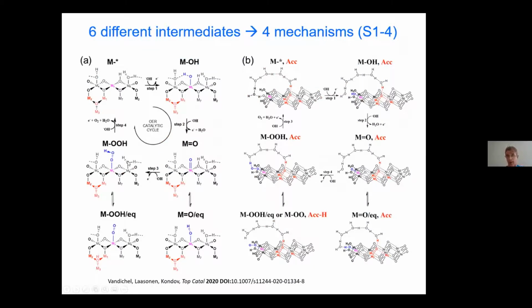So again, different states have been investigated. It's always quite similar methodology. Now, the hydrogenated acceptor site has been named as an equilibrated metal OOH species. And we can also work with an equilibrated metal oxo species. So then this hydrogen at the edge jumps onto the oxo, and this can be more stable for some metal oxyhydroxide edges, not for all of them.